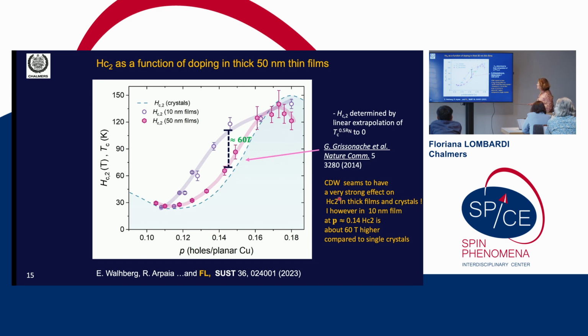Okay, so what we did, we needed a test experiment to see if the HC2 fields for our thin films, which are conventional bulk, I would say, as a function of doping, were following the same dependence as for single crystals. And these are the rose curves here, rose points here, and the dashed one is what has been measured for single crystals by the Taillefer group. And you see that we get a pretty close dependency here. And this is interpreted as why the HC2 is depressed as a function of doping. This has been interpreted with a competition between charge density wave and superconductivity, because this charge density wave quasi-nesting removes states, and there are fewer states available for superconductivity. You have a reduced TC and reduced HC2.